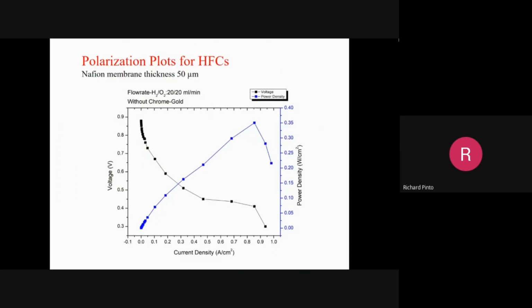Now, here you see the polarization plots of HFCs. The Nafion membrane thickness is 50 micron. We took 50 micron because Nafion 50 micron is the optimum. Anything less than 50 micron, there is a reliability issue. With 50 micron, we found a large increase in the power density.